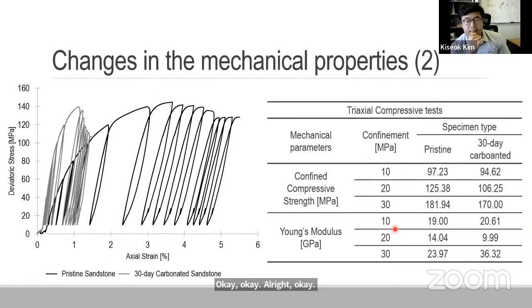Okay. Another question: it was quite interesting to see that your Young's modulus was increasing while your strength was decreasing, and at the same time, for your hydraulic measurements, your porosity was decreasing while the permeability was increasing. Just intuitively thinking, they are going against each other in both cases. Do you have any explanations for those results?